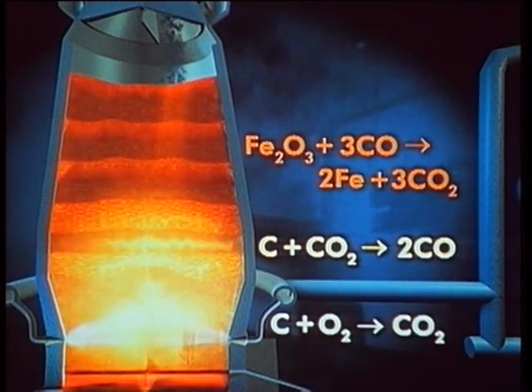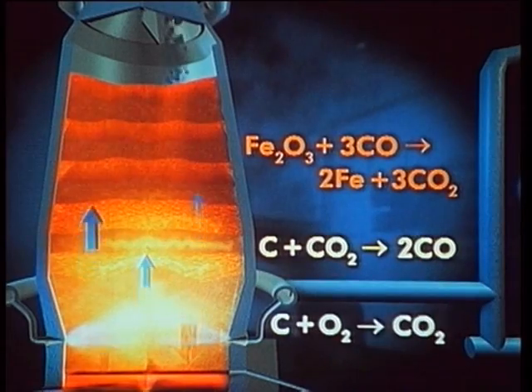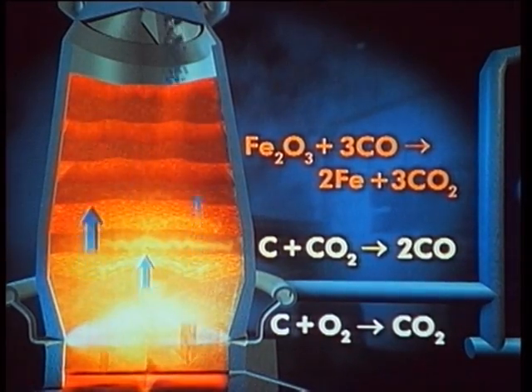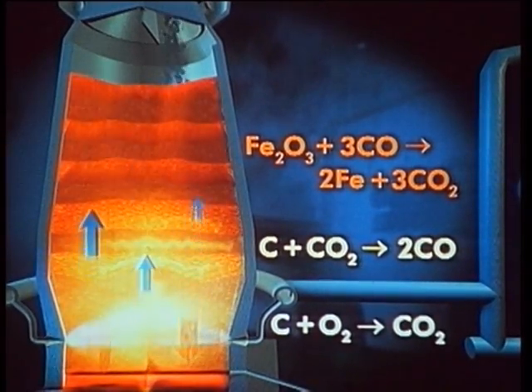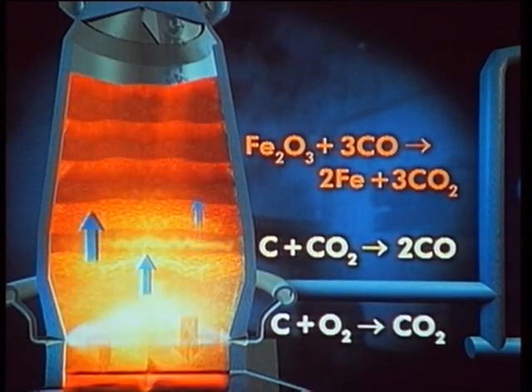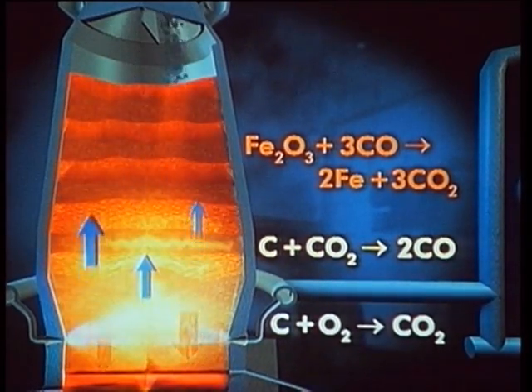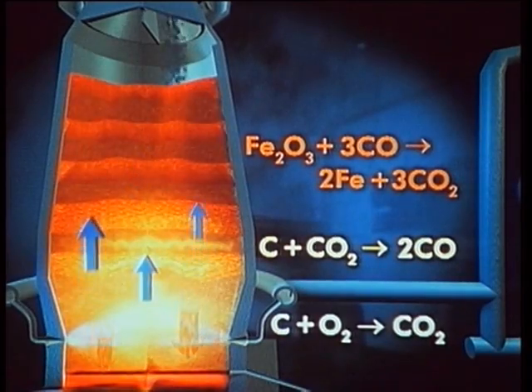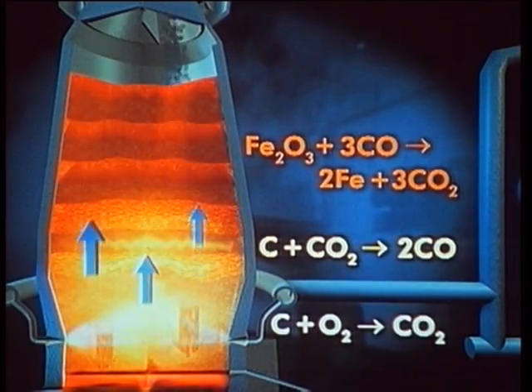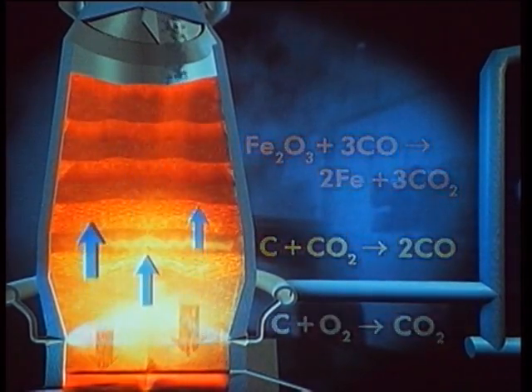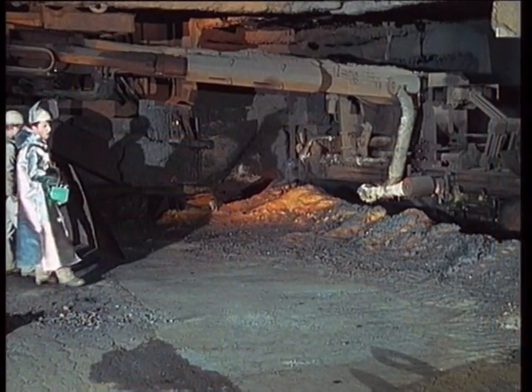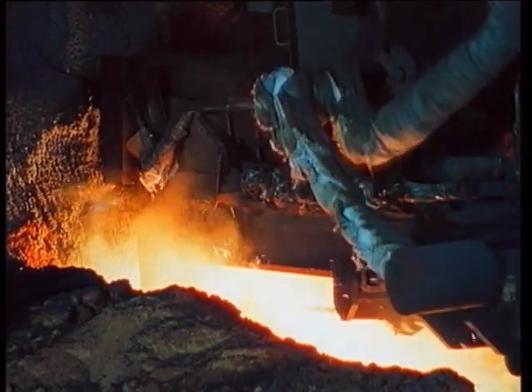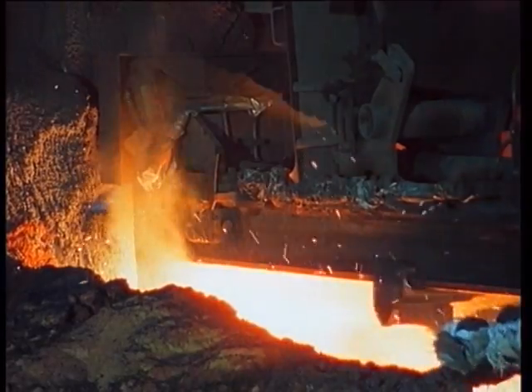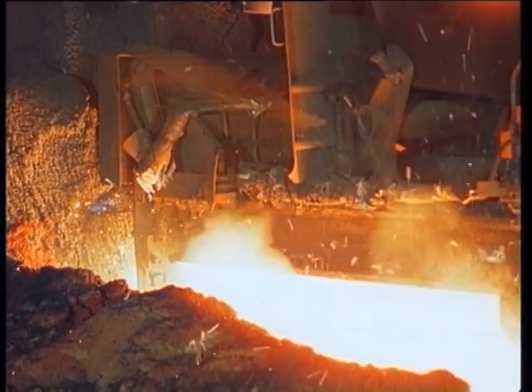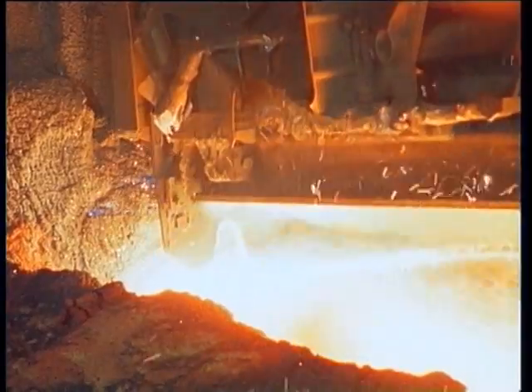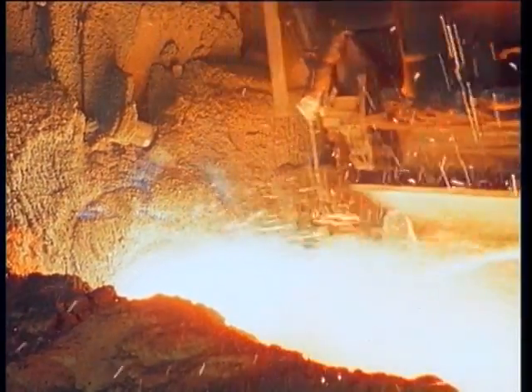As the ingredients continue downwards, liquid iron and slag is produced. The carbon partly dissolves into the pig iron. Hot gases rise and preheat the descending raw materials. Near the bottom of the furnace is a hole through which the liquid iron flows when the sealing plug is tapped. A modern furnace can produce about 11,000 tons of pig iron per day.